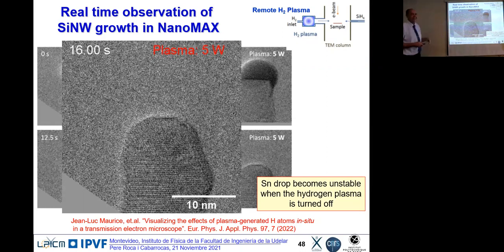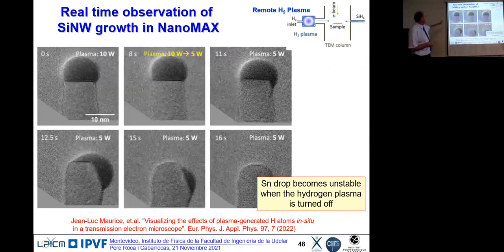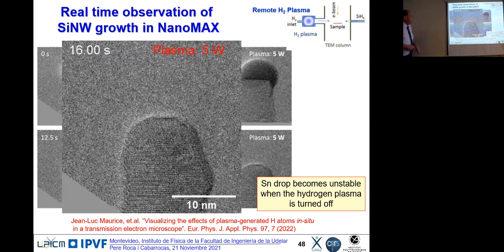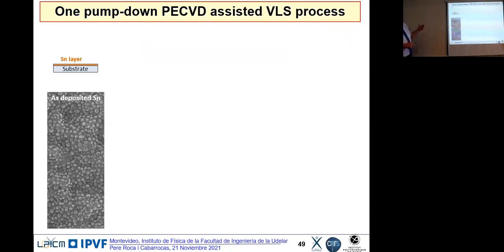So just to show, because it's a function of power, we have 10 watts, everything looks nice. You decrease it still, but then you see that it starts to flow. The surface tension wins. The surface energy here wins and makes the drop fall down. And it's not that it falls, it's that if the wire was like this, it would have been the same. It's the surface energy.